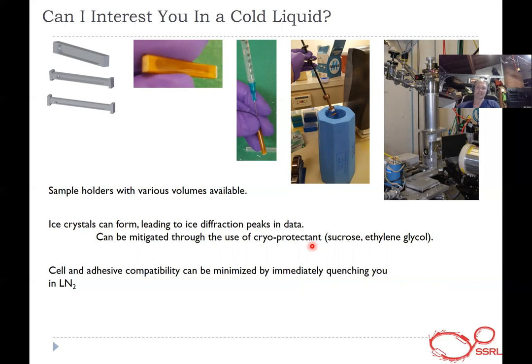Ice crystals can form in this case, depending on your solvent, so those can be mitigated in a lot of cases with a cryoprotectant. Dissolving sucrose or ethylene glycol into your solution will help with that. Cell adhesive compatibility issues can be minimized by immediately quenching your sample in LN2. Like I said, if your sample might dissolve the adhesive semi-slowly, you can quench it real quick and prevent leaking, also because the contact area for the adhesive is pretty small.